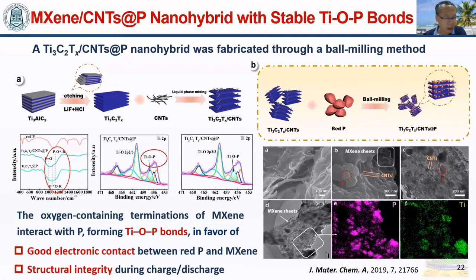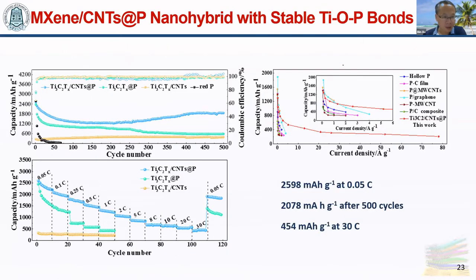Due to the high capacity of phosphorus, the good conductivity, and also the stable Ti-O-P bond, the nanohybrids exhibit a very high capacity, about 2,600 mAh per gram. It also shows a very stable cycle performance and very good rate performance. It can output 450 mAh per gram at 30 C.